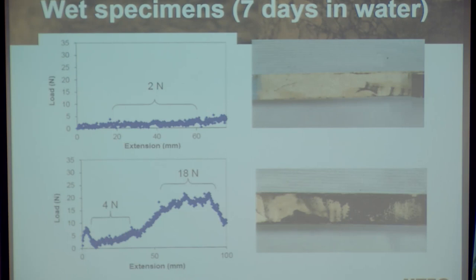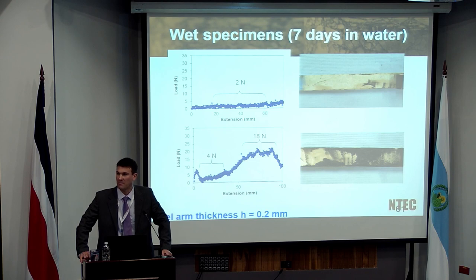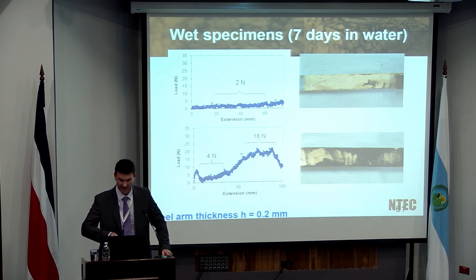But I think more importantly, we now start to see the influence of moisture damage, that change in failure mechanism from a cohesive failure in your dry specimen, where everything is sticking nicely together in terms of the bitumen and the stone, to some form of debonding or stripping. In other words, some form of adhesive failure. So straight away, this test is allowing us to not only determine a value in terms of the fracture strength, but also to identify the actual mechanism of failure. And that's quite important in terms of understanding the combinations of different aggregates and different bitumens in our materials.